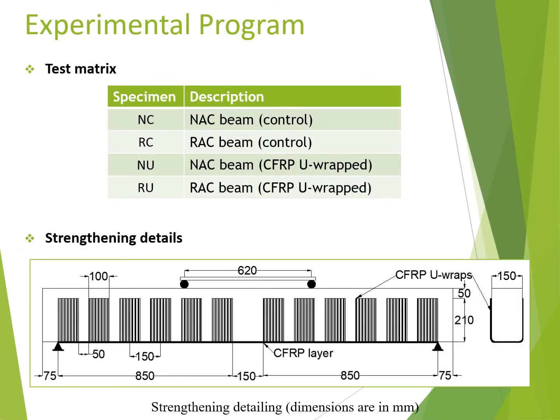A total of 4 reinforced concrete beams were tested in the study. 2 specimens were cast with normal aggregate concrete and 2 specimens were cast with recycled aggregate concrete. One of each specimen was left unstrengthened to act as a control specimen. And then the other 2 were strengthened with CFRP U-wraps, as you can see here.